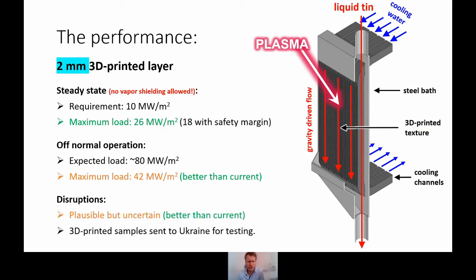And then finally, there are the disruptions. Disruptions, just to put into perspective, are still about 100 times more severe than the pulses that we tested in Magnum. So this is a really, really difficult thing to assess. Based on our modeling and the experimental results so far, we think it should be plausible. And that is already a huge improvement. But just to be sure, we have filled these 3D printed samples of ours with tin, and we have sent them to Ukraine. So in the coming months, they will be tested, and this will be a very exciting result, actually.